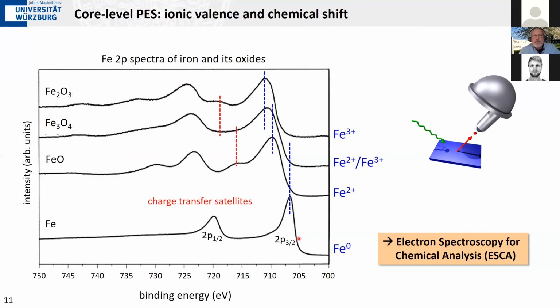And the bottom curve you see here is iron metal. That's just plain metallic iron. And then here we have three different oxides. The degree of oxidation increases from bottom to top. This is iron monoxide. On the top we have iron sesquioxide, Fe2O3. And in the middle we have magnetite, Fe3O4. What changes as you go from the metal to these more and more strongly oxidized oxides is the valency of the iron ion in the compound.